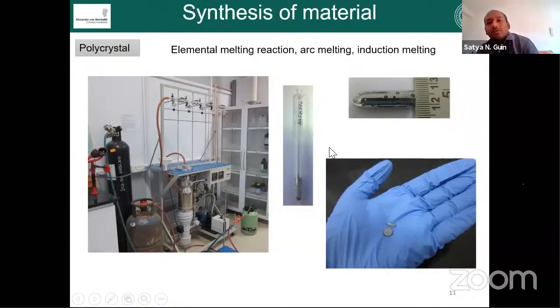Now, how do we make a good thermoelectric material in the lab? How do we generally do the synthesis of thermoelectric materials? Different materials can be synthesized in polycrystalline form, for example using high vacuum sealed reactions, where you seal the material in a quartz tube and get an ingot, which you can cut into bar and coin shapes for the thermoelectric measurements.